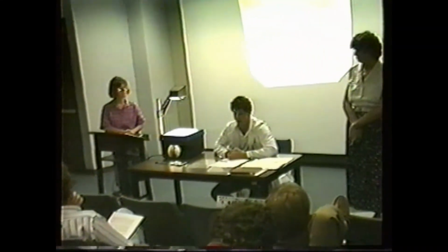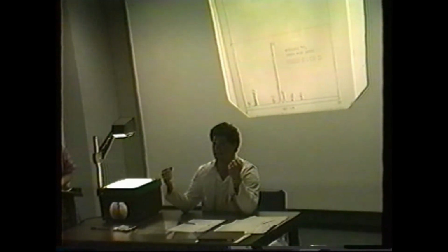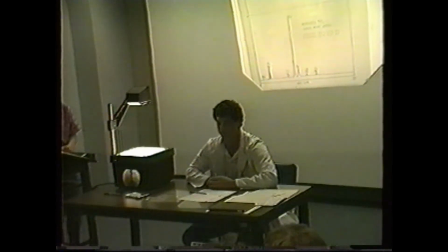Would there be any possible radiogenic methods? Yes, and we could once again do lead isotope ratios, as we talked about in the preceding one. The problem with that is that it doesn't specifically tell you the exact date and time. What can be done is to compare to other Raphael pigments, and specifically say that yes, this was a pigment used or no, it wasn't. But as far as dating, lead isotope is not really a dating type analysis. It's a comparative type analysis.